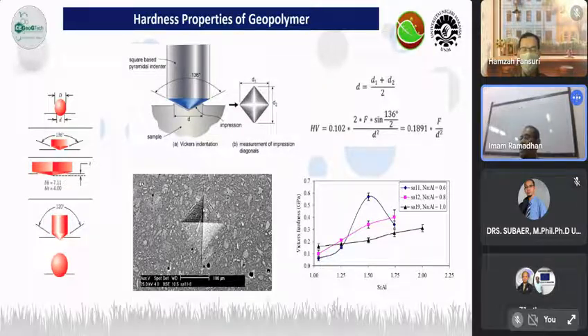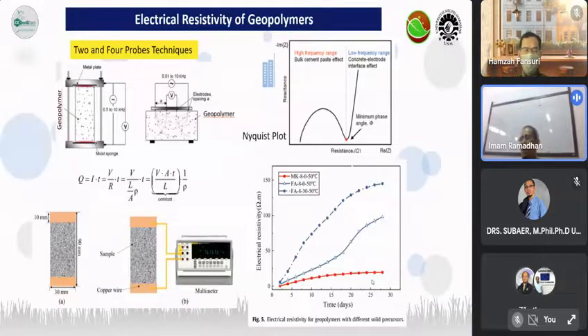Very nice. You apply a load of around 2 kilograms for 20 seconds, then you can have the hardness of your materials, and it will change as a function of silicon aluminum or sodium aluminum or other parameters you can think of.